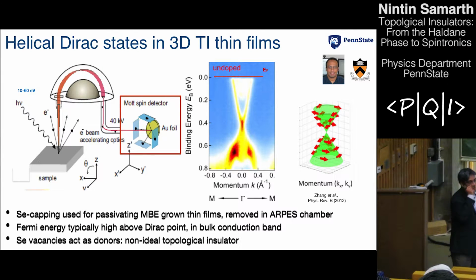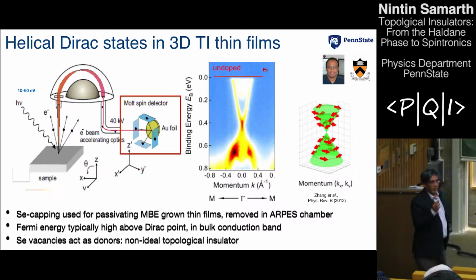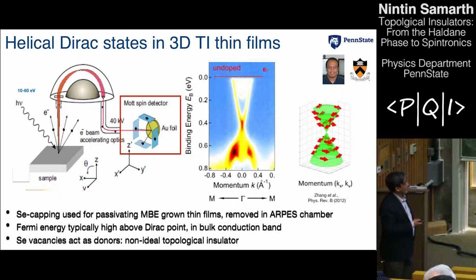Once you make samples of this kind, you want to find out whether these surface states exist on the samples. And since we can't do it in our own chamber, in our own facilities, we've been collaborating with Zahid Hassan at Princeton University. And the way we do this is that we take our samples, we passivate the surface, we protect the surface with a special kind of layer. It's a layer of selenium. And they can then take this into an ultra-high vacuum chamber, evaporate the selenium, and they can see very clean energy spectra that are corresponding to these surface states.